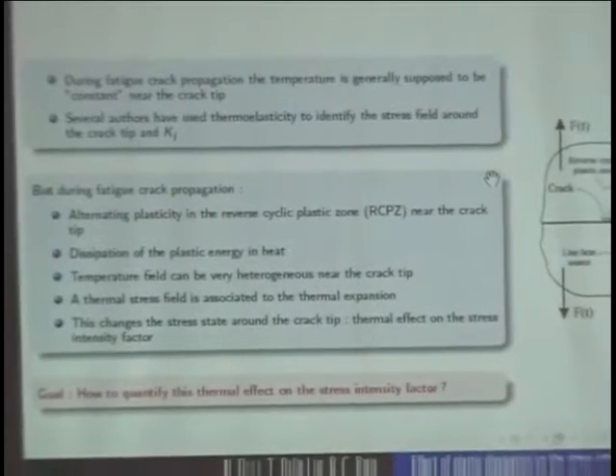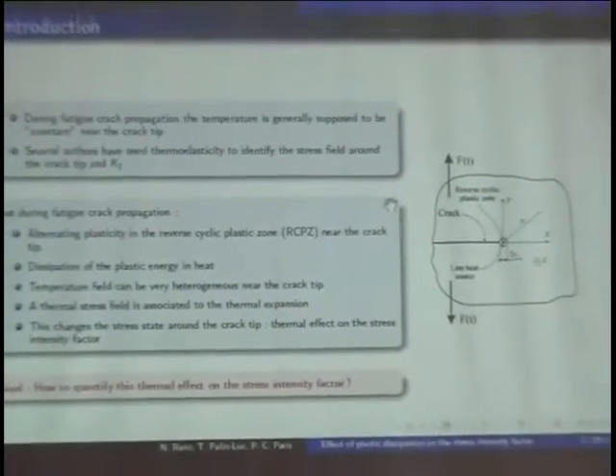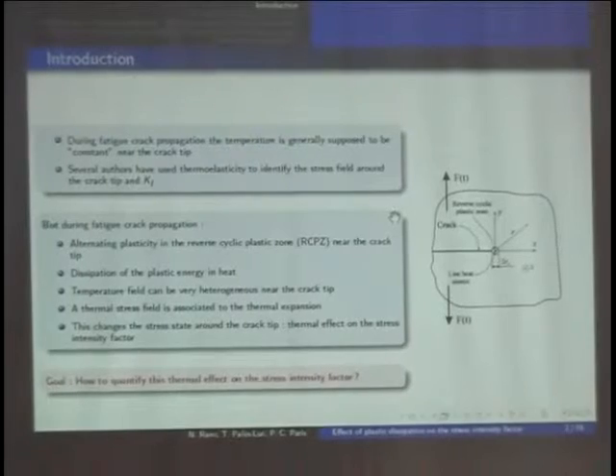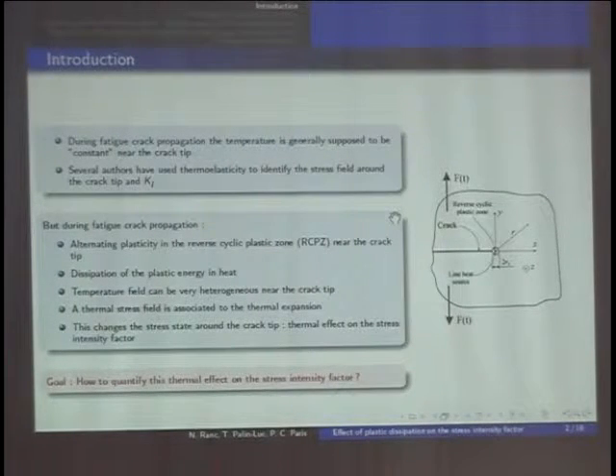Due to this dissipation in heat, the temperature field around the crack tip is heterogeneous, and consequently there is a thermal stress field associated with the thermal expansion, because around the crack tip the material tries to expand, but it cannot because of the rest of the material, which is elastic. So how to quantify this effect of the temperature on the stress intensity factor is the main goal of the presentation, in the theoretical case of the large plate with a large crack.